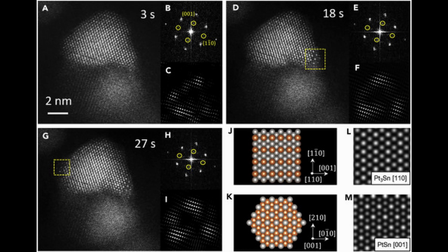The formation of a platinum-tin alloy and the partial covering of the platinum particles by tin species result in the creation of small platinum ensembles. Tin can selectively cover low-coordination platinum sites such as steps, corners, edges, and defects, which are believed to be responsible for the hydrogenolysis reaction. The so-called ensemble effect can be employed to explain the geometrical advantage of tin addition to platinum-based catalysts.